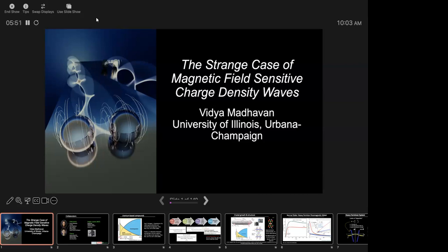So you can see from the title that something very strange goes on in this material, apart from the cool superconducting properties. What we found in this system is a very exotic charge density wave, which responds to magnetic field. And what you'll see is that it responds to magnetic field in a very peculiar way, meaning that the charge density wave actually dies when you apply field at values close to HC2. So charge density waves are not supposed to actually disappear with magnetic field, and especially not at values close to HC2. So this immediately tells you that the charge density wave in the system is somehow tied to superconductivity. So that's partly what I'm going to talk about today, after sort of an extensive introduction to this material.